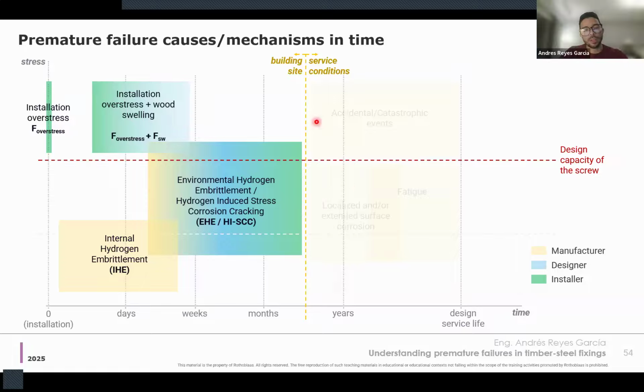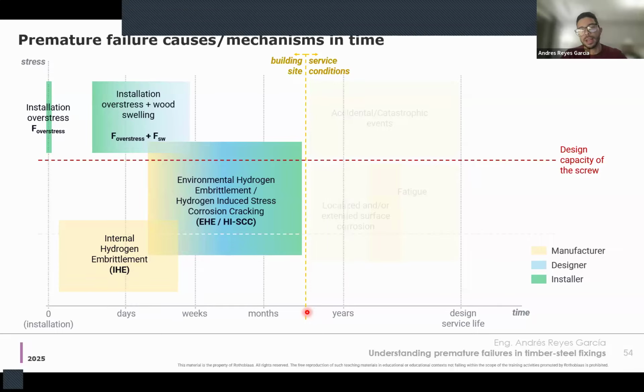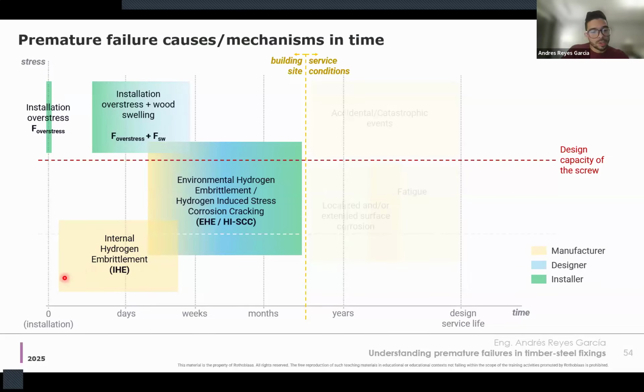Yeah, that's one of the reasons I wanted to. This line is very important because hydrogen embrittlement in general, whether it is internal or environmental, is a problem of the construction site. Internal hydrogen embrittlement doesn't require an effect of moisture, so it can happen from hours after the installation to days after installation, no more than that. It doesn't take much stress, and the installation stress is enough for internal hydrogen embrittlement to activate.